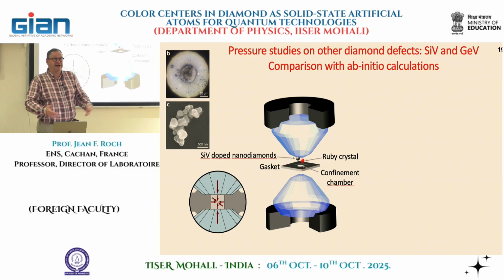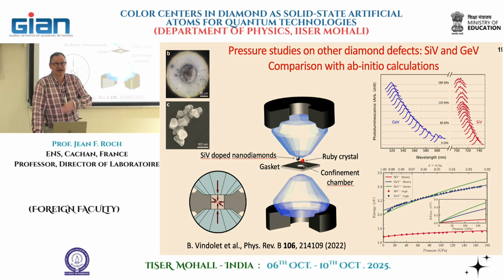Okay, we can apply the same technique to investigate how pressure acts on other defects of diamond. So for instance, silicon vacancy, germanium vacancy. So these are nanocrystals that embed these defects. You integrate them and you try to observe, for instance, how their spectrum will change with pressure. This is a very preliminary experiment.